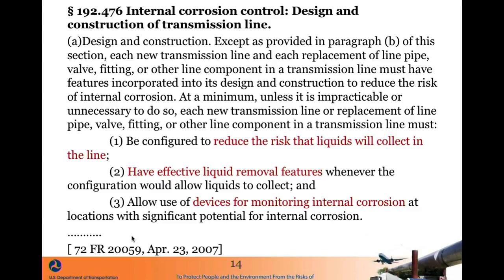And this refers to that to reduce the risk of liquids that may collect in the line. And so natural gas pipelines must have effective liquids removal features, and you must have devices for monitoring internal corrosion. These typically occur in low spots or drips in the line, or parts of the natural gas line that may have stagnant flow, where more water may sit. So if there's no water there, pretty much, you will not have internal corrosion.